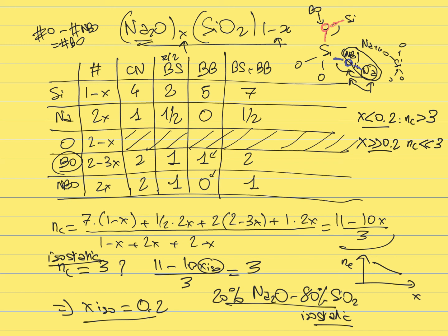So typically in these types of glass, you can still form a glass anywhere between x from 0.2 up to 0.4. But any x that is much larger than 0.4 would give you a glass that becomes too flexible, where the number of constraints is too low as compared to 3. And in that case, you would have a very low glass forming ability. It would very easily crystallize.